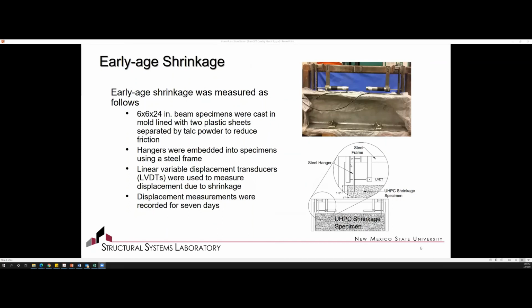We also looked at shrinkage, and we looked at early age shrinkage just because, as shrinkage occurs, we know this is going to develop stresses between the substrate and the overlay. So we wanted to make sure that we could accommodate that. We had an idea of what we'd expect in the field, and so we looked at early age shrinkage by looking at small prisms. Essentially, we were monitoring the strain that was being developed over the first 7 days for the early age shrinkage. You can see the test setup there. That enabled us to monitor and capture those deformations in the UHPC specimens.